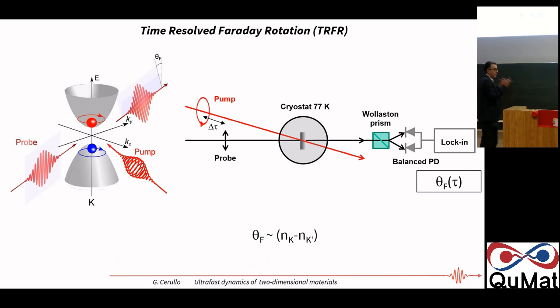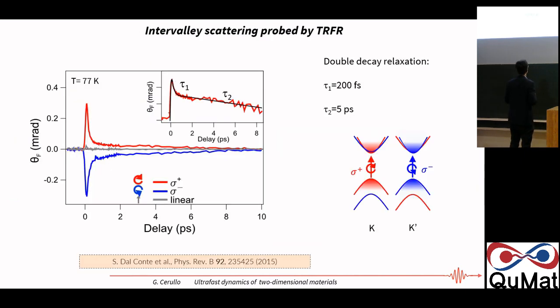So if the spin up and the spin down carriers are equal, there is no rotation, so we will see zero signal. If there is more of one valley, we will see a positive signal. If there is more of the opposite valley, you will see a negative signal. This measurement can be done really sensitively if we use a Wollaston prism to separate the two orthogonal polarizations and a balanced photodetector. This is similar to what is used in terahertz detection. You can really make very precise, very noise-free measurements. And this is what we did on MoS2, but now we have repeated it on a number of materials.